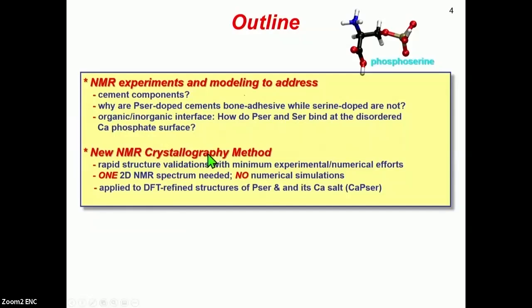And this has several advantages. It gives rapid validation of potential model structures with a minimum of both experimental and numerical efforts. You only need to record 1 2D NMR spectrum. There are no numerical simulations involved. And we have applied this to DFT refined structures of phosphoserine and its calcium salt.